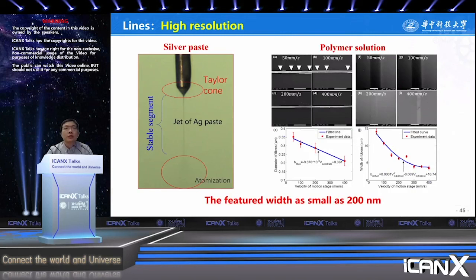The EHD direct writing is also determined by the solution. There are 2 kinds of high viscosity solution. One is like a silver paste that is broken easily. Another is like honey, such as a polymer solution, which is difficult to be broken. For the paste, one can only use the stable segment to write pattern.